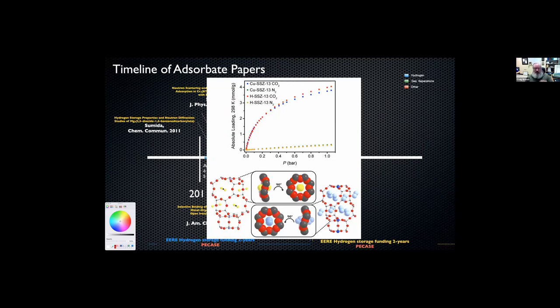Matt was looking at CO2 adsorption in some zeolites. And because of the quadrupolar interaction between the dipolar CO2 and this 8-membered ring in the chabazite SSZ-13 zeolite, there's a really strong interaction for CO2 within that ring for low aluminum content silicates. If you go to really high aluminum silicon contents, and especially the potassium kind, there was some work done by Paul Webley in Australia where you can get essentially a gate blocking mechanism because the cations start populating those 8-membered ring sites and it stops the CO2 being able to diffuse into them.